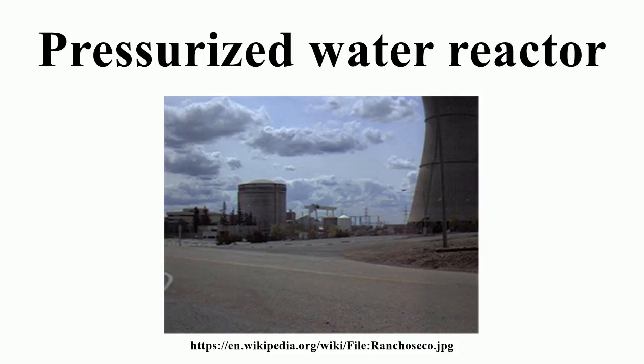The high-temperature water coolant with boric acid dissolved in it is corrosive to carbon steel. This can cause radioactive corrosion products to circulate in the primary coolant loop. This not only limits the lifetime of the reactor, but the systems that filter out the corrosion products and adjust the boric acid concentration add significantly to the overall cost of the reactor, and to radiation exposure. In one instance, this has resulted in severe corrosion to control rod drive mechanisms when the boric acid solution leaked through the seal between the mechanism itself and the primary system.